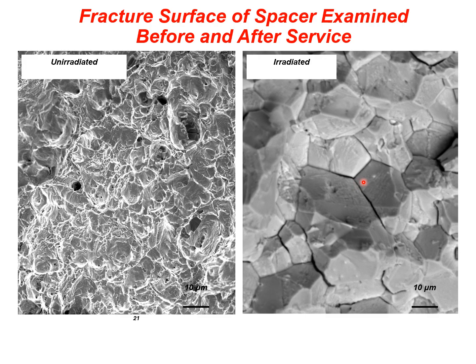And that's because in a CANDU reactor, we produce tens of thousands of atomic parts per million of helium over a 10 to 20 year reactor operation. So after 30 years of operation in a CANDU reactor, there's something like 30,000 atomic parts per million of helium generated.